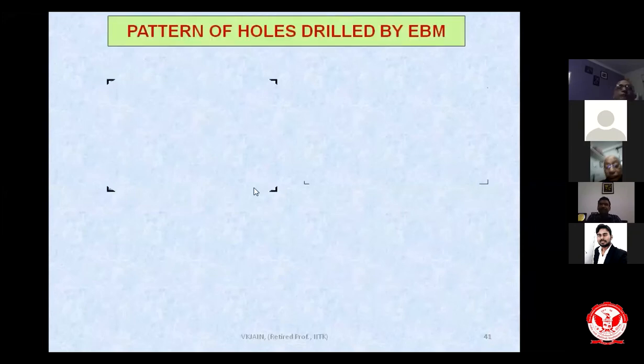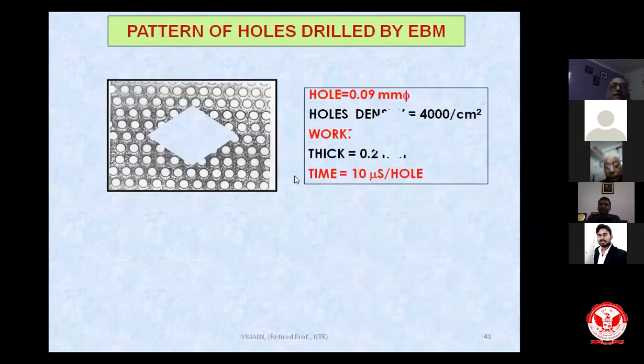Now, with the help of electron beam micromachining, some industry people created 90 micrometer holes with a density of 4,000 holes per square centimeter on stainless steel. The thickness of this sheet is 0.2 millimeter, and the time taken is just 10 microseconds per hole.